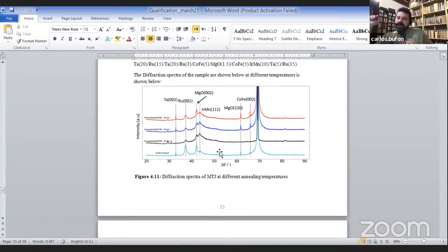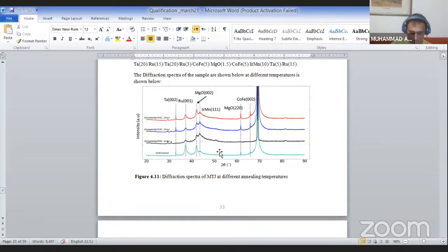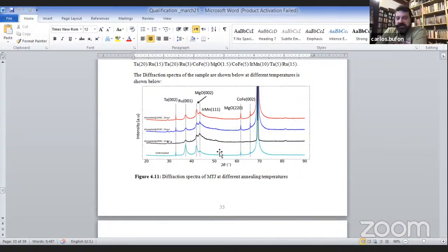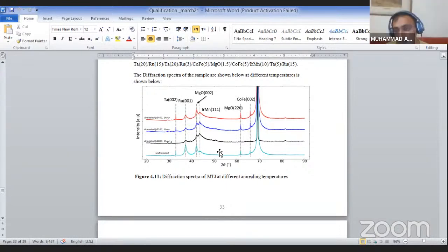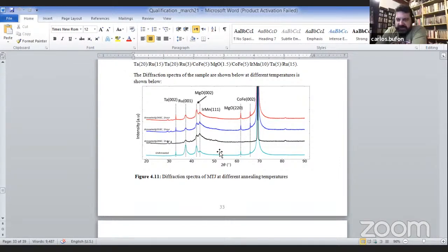Actually, not really, depending on the condition. Actually, if you have amorphous and apply heat treatment, you actually create polycrystalline structures. That's a bit controversial. My point is, if you have amorphous or polycrystalline, can you distinguish this from your measurements? We do the XRD of our samples for checking the crystallization or amorphous state of our samples. Okay, so then you measure with XRD. Yes. And then you can be sure that it's amorphous because you measure the X-ray diffraction. Yes, Professor. Okay, so that's what I was expecting to hear from you.